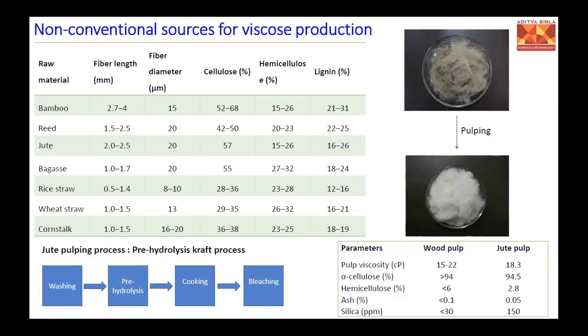This is the viscosity. Now I'm comparing it with the wood pulp or the dissolving pulp, which is generally used in the process. Typically the viscosity of the pulp is around 15 to 22 cp, whereas the viscosity of jute pulp is 18. So it is a pass. Then alpha cellulose is also required, I said 93, 94%. Again, jute pulp has very high alpha cellulose, so in this criteria also jute pulp passes. Hemicellulose is also less. So ash content is also less.